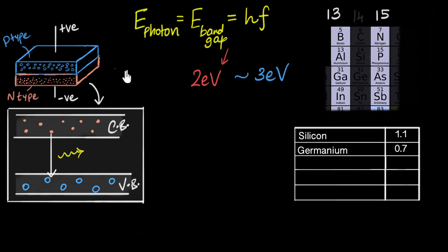And if you do that, turns out their band gap, for example, gallium arsenide, a mixture of gallium and arsenic, that gives you a band gap of about 1.4. And if you mix gallium and phosphorus, that gives you gallium phosphide, and gives you a band gap of about 2.3. Higher band gaps than our usual semiconductors. So gallium arsenide is 1.4, and it's still not quite there, but this is useful for infrared. We're now in the infrared region. And gallium phosphide, now it's in the visible region. 2.3 turns out to be somewhere around green.